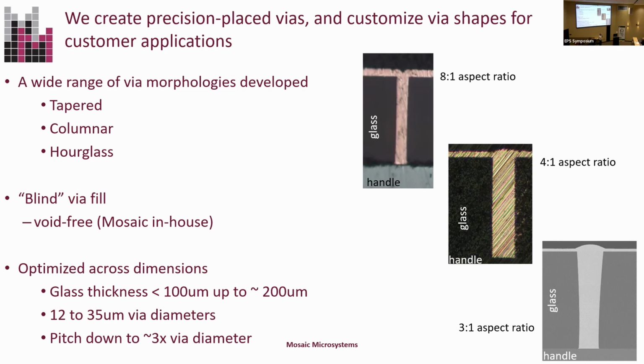There's the overburden. So now you've taken the thin glass with TGVs and you've created something that is the same to fill as, again, the industry is sort of used to with TSVs. It's a blind fill. We can do very columnar vias, as you can see in the 4:1 aspect ratio via in the middle. And we also can do very narrow, deep vias, so aspect ratios up to 10:1 we've demonstrated.